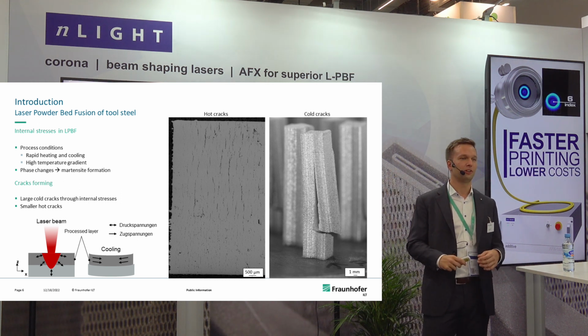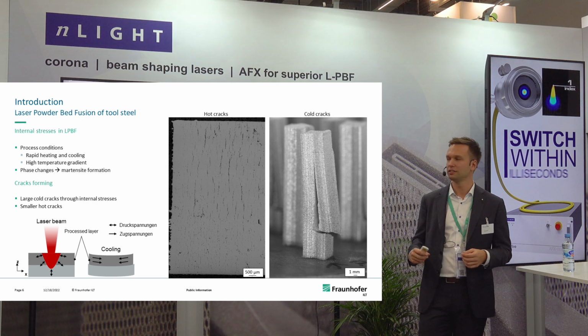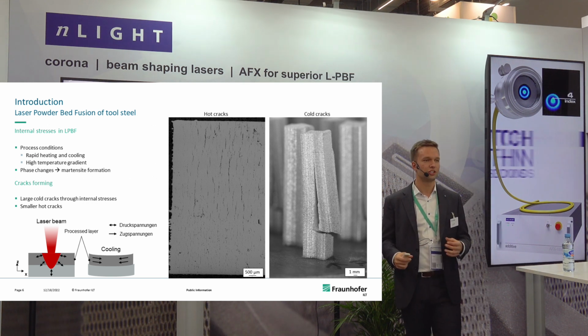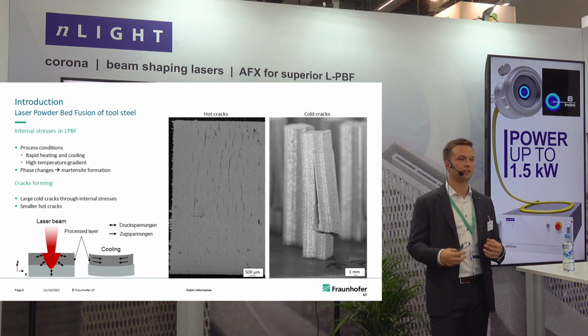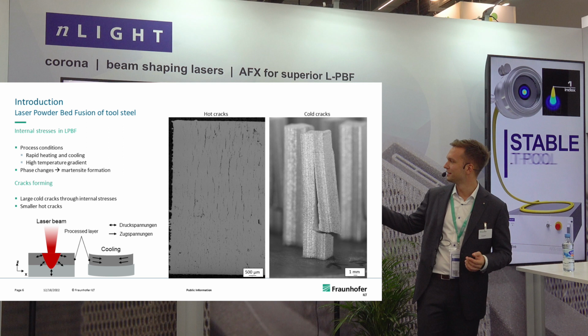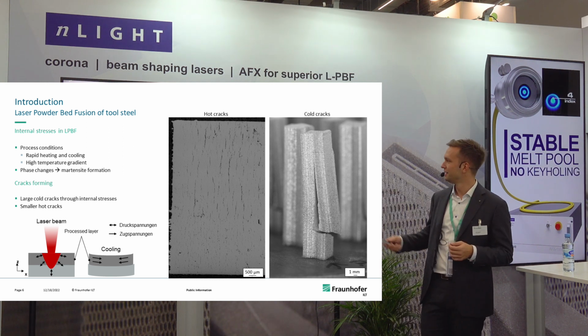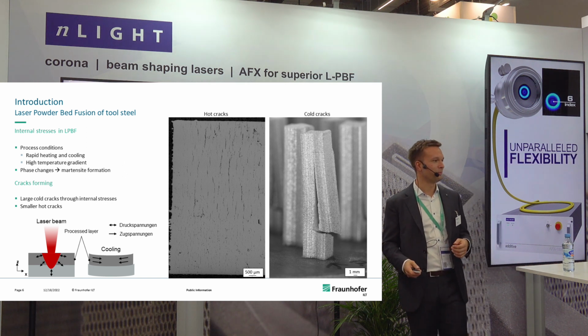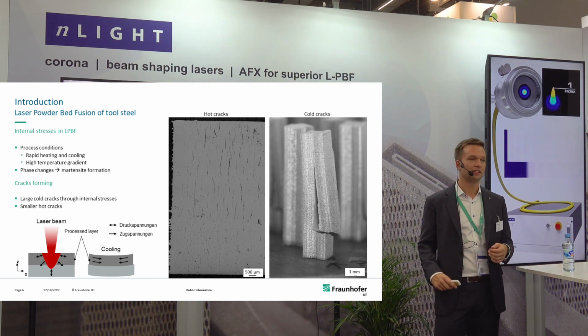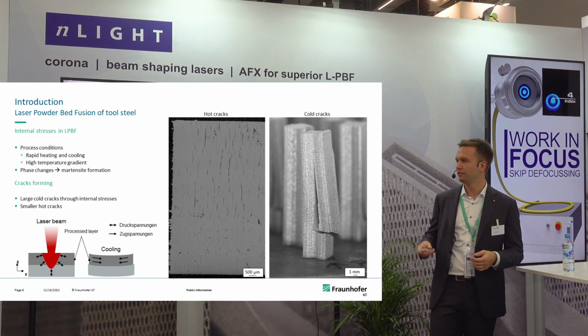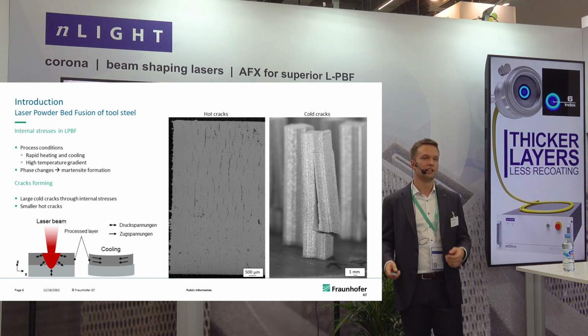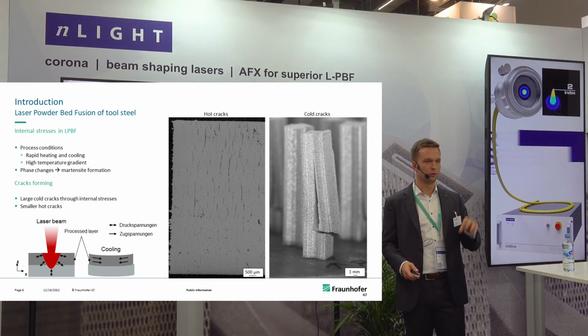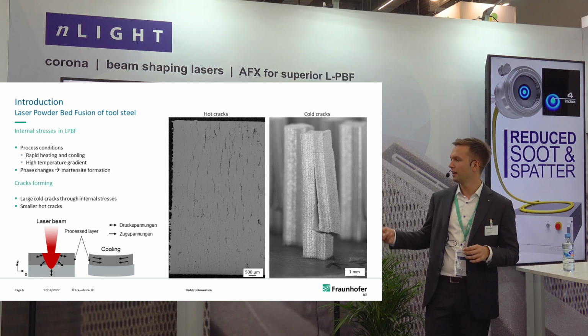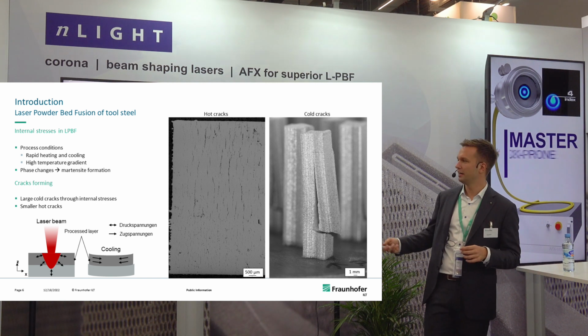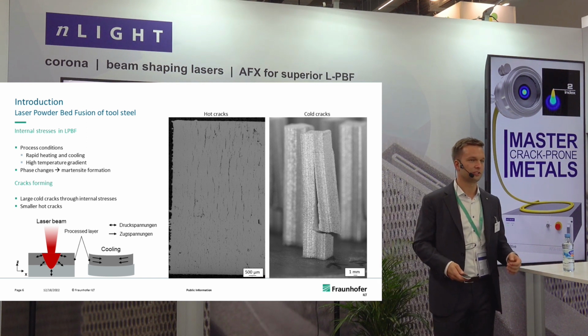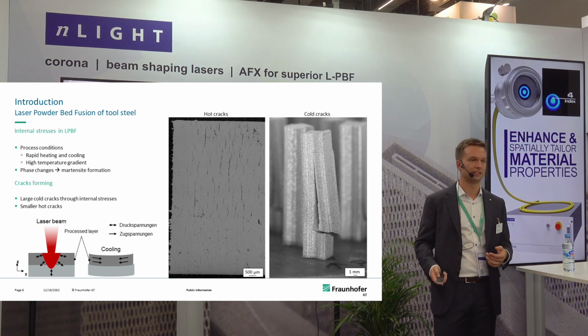Either you have a lot of hot cracks that form during solidification, or you end up with large cold cracks when you cool down the parts after the build, and then have cracking of the entire part. In some cases, as you see, several millimeters of deformation just due to cracking. And these result from the complex temperature fields we have in powder bed fusion. So usually you have quite regular heating and cooling cycles which happen very fast. You have discrete solidification and therefore inner stresses that can build up and then as a consequence lead to these defects in the component.